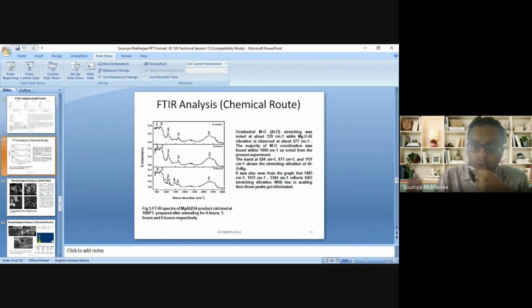For the chemical route, we are getting almost the same result, especially the metal oxide coordination part, which is clearly around 530 cm^-1 for aluminum oxide presence. For magnesium aluminum oxide, we are also getting around 677 cm^-1, and some peaks for hydroxyl ions, H2O, which are mainly due to the chemical route process, but with a more increased soaking duration, these peaks are almost neglected.